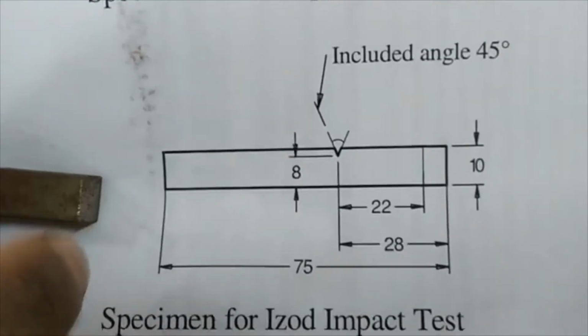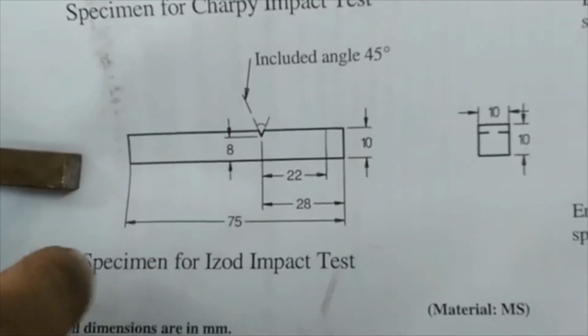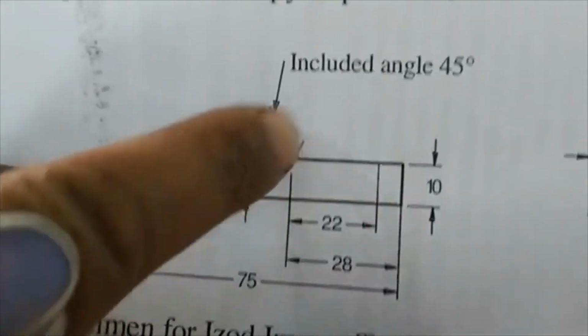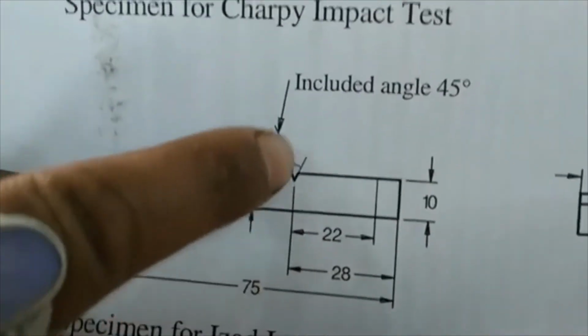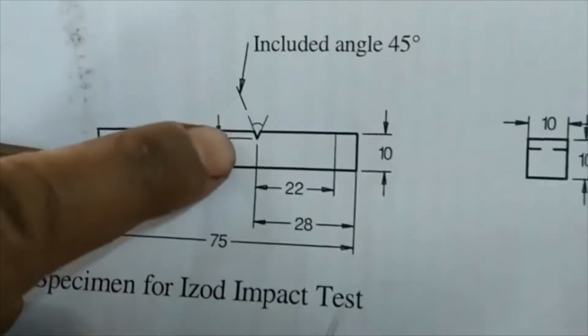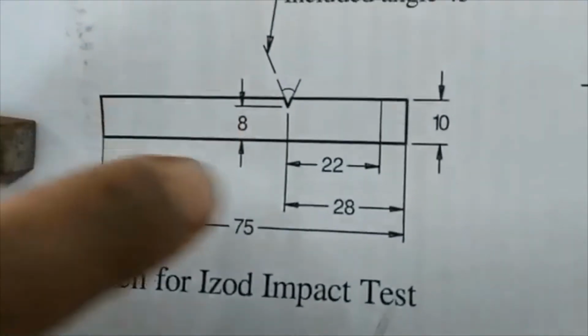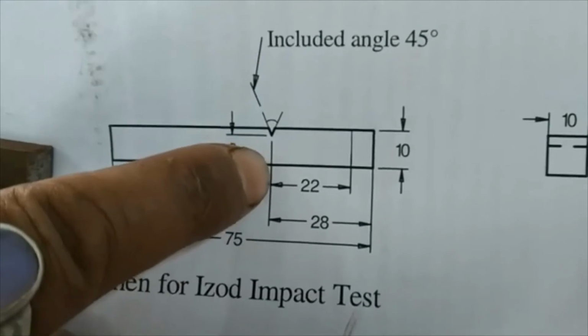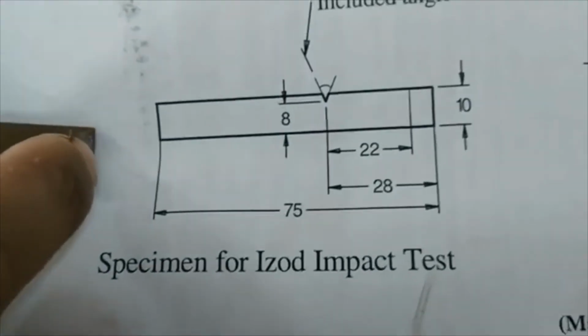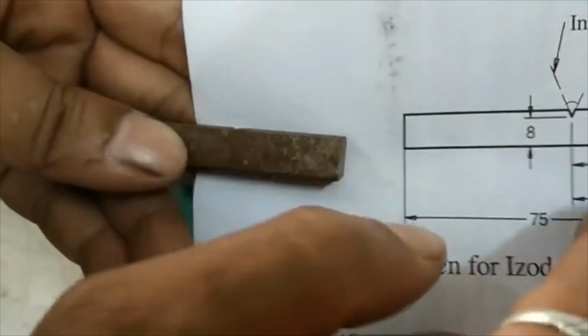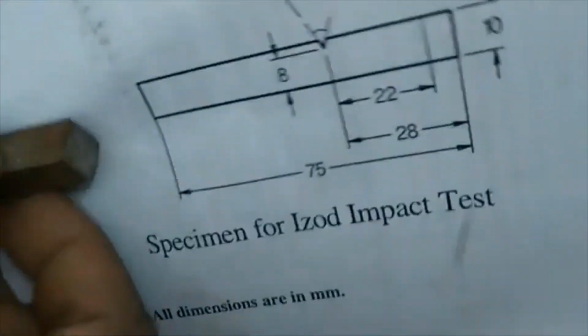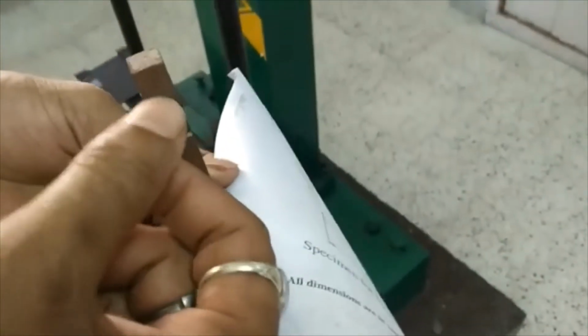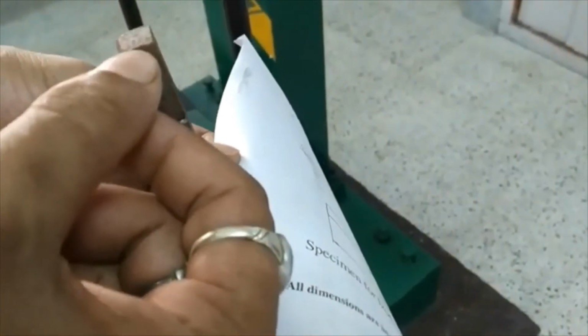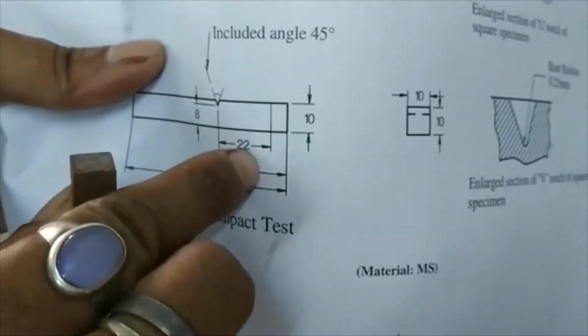10 by 10 in width and thickness, and this is the notch. This is a V notch, the notch geometry. Included angle 45 degrees, and depth of this notch 2 mm. From the notch position to the top, length 28, and the striker will strike in front of this notch, 6 mm below the top. That means 28 minus 22, so 6 mm below, the striker will strike.